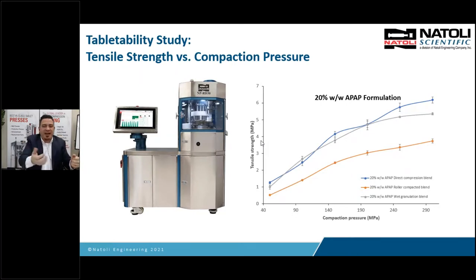So if someone says I have a hardness of 50 KP, that might sound very high to me, but if my tablet is this big, it's 3-inch diameter, 50 KP is not high at all. But if I convert it to tensile strength, where I take the hardness divided by the fracture area times pi, it takes into account the tablet geometry, the hardness, and it normalizes that hardness into a pressure. So now it's independent of size. We typically target between 1 and 2 megapascal tensile strength.